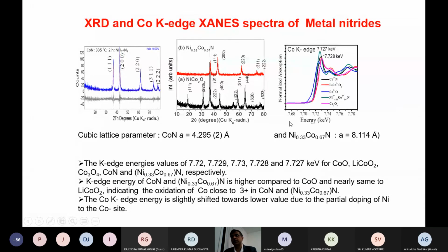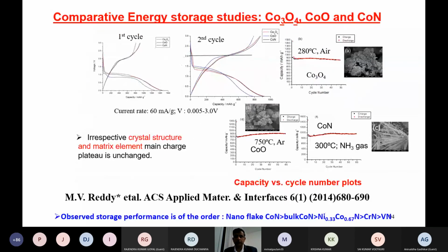And we check the lattice parameter as well as the X-ray absorption fine structure. There we can tell, based on the reference, whether the cobalt edge closely matches the standard compounds or not. So as for energy storage applications, we've still been focusing on different types of materials, and in reality I think it is a very interesting material. Then at the end, for large scale applications, we have to reduce the potentials for the real applications.